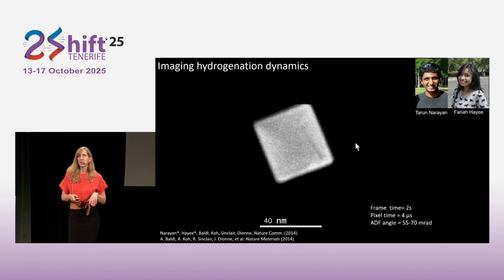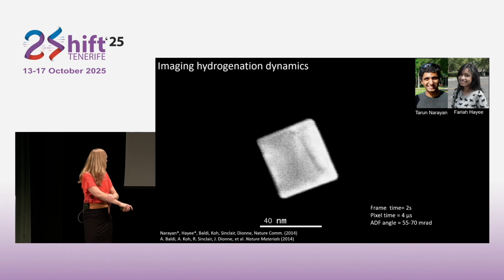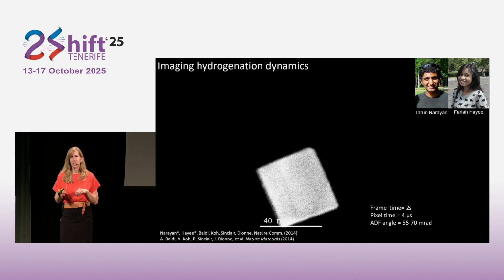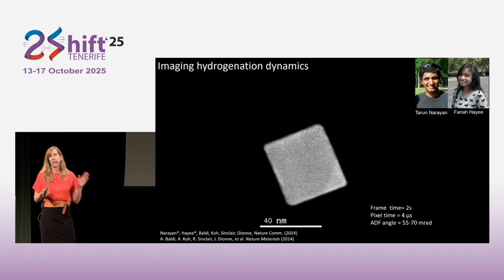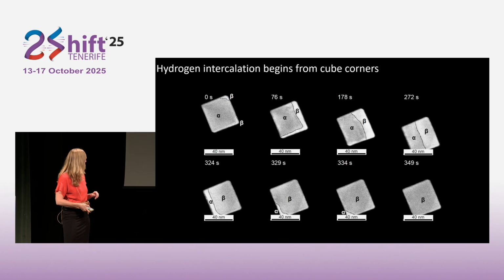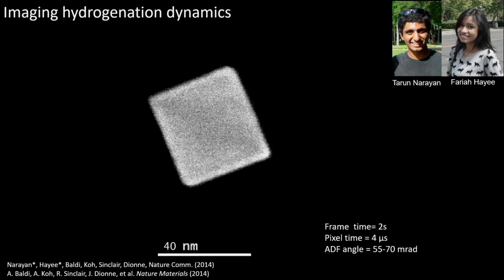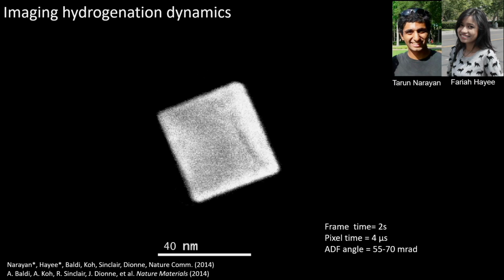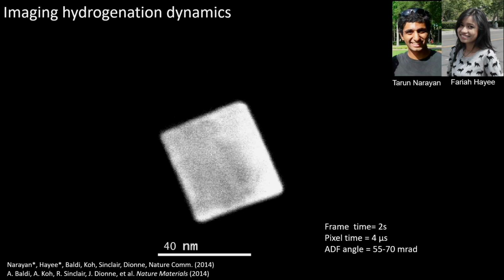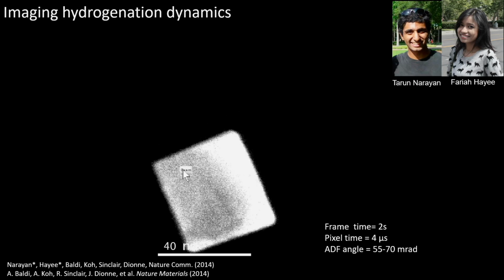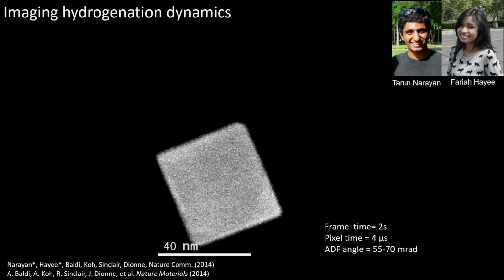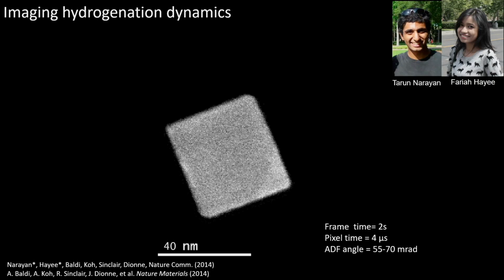So I won't go through the details of how we do all of the experiments, but here was one of the early experiments now from, I guess, about almost 10 years ago, where we were actually visualizing the kinetics of hydrogen intercalating into a pure palladium nanocube. And you'll see as the talk goes on how our resolution has improved. But if I play the video one more time, hopefully it'll let me. Maybe I'll go back one slide. Here we are. You can see that the corners of the cube start turning white. That's actually where hydrogen is starting to intercalate into the cube. Eventually, the hydrogen starts to linearize across the cube and then propagates across the entire cube until it's fully hydrogenated.